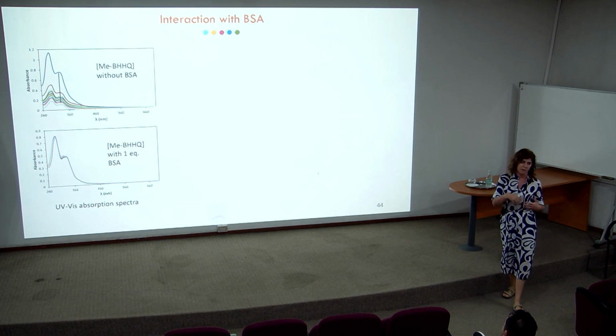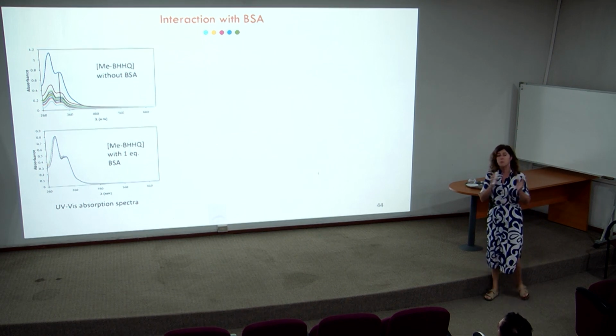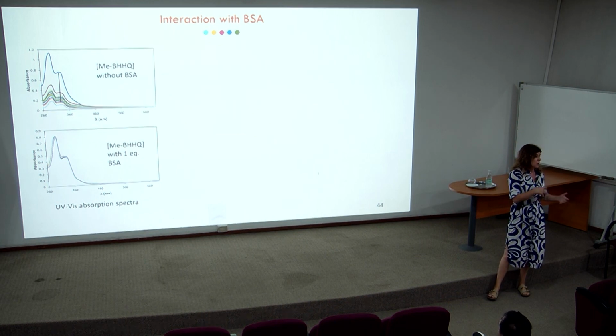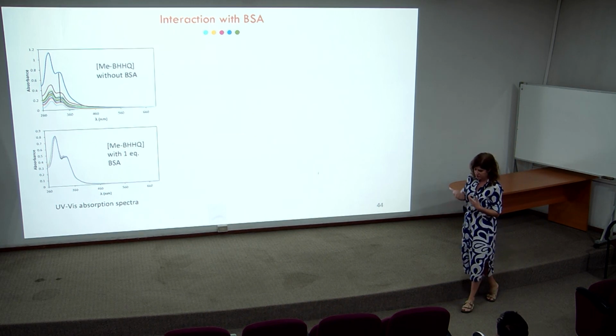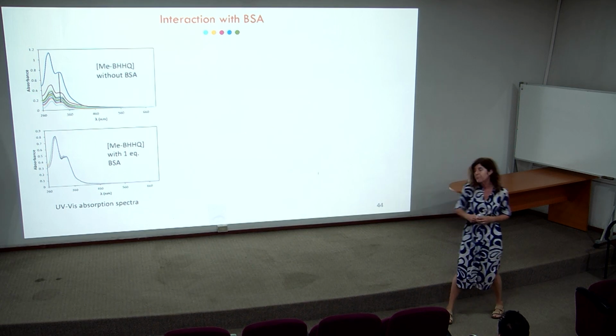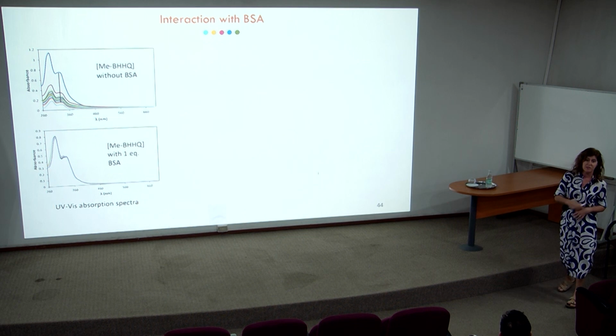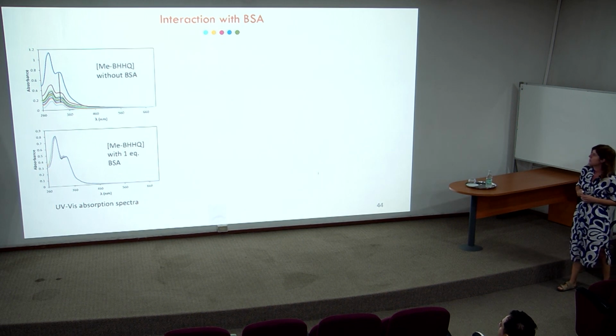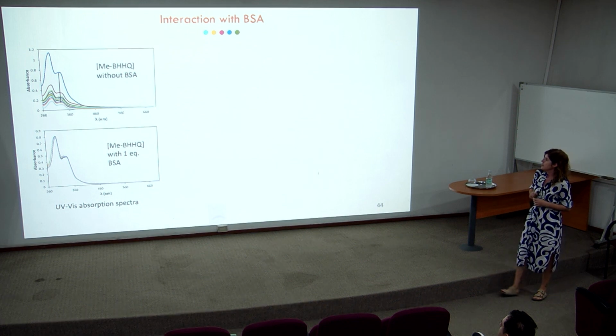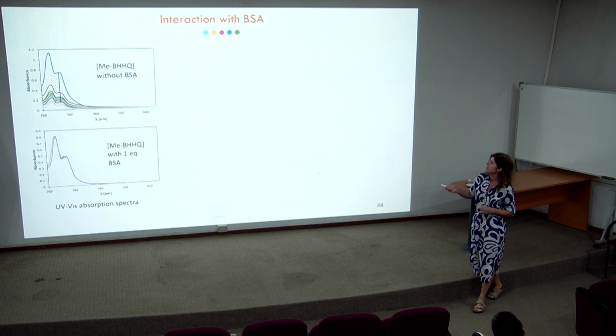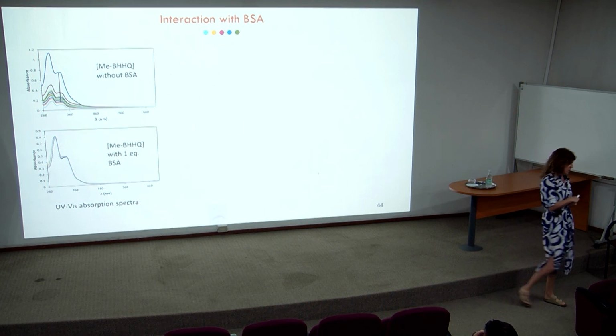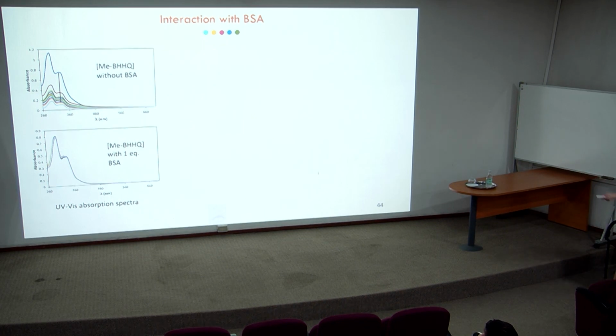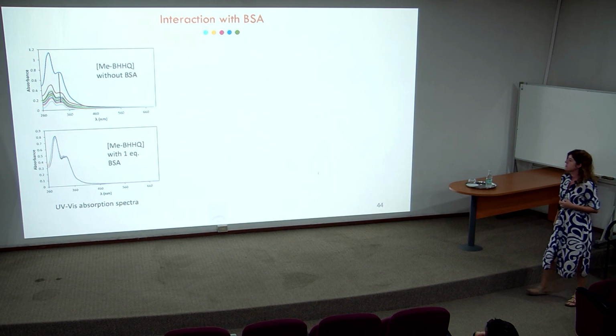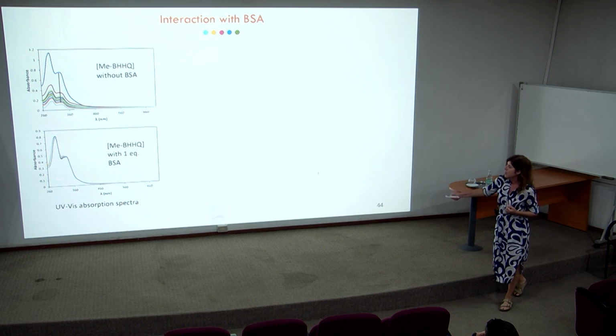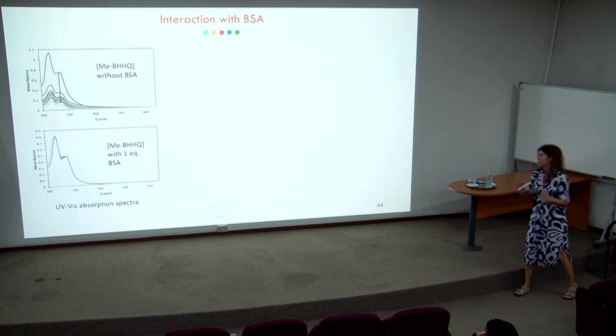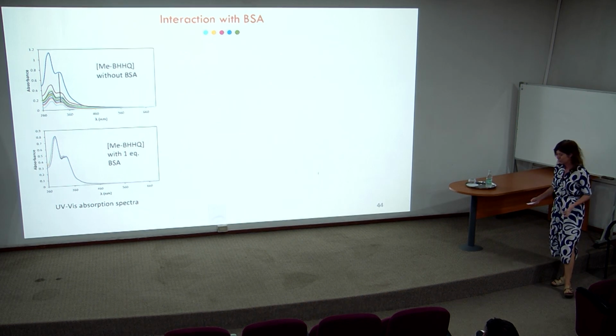We always evaluate the interaction with BSA. Bovine serum albumin can be considered a model also for the human serum albumin, which is the most abundant protein in blood serum, and it is a transporter of many drugs. So we always evaluate the interaction with bovine serum albumin, and we can see that in the absence of BSA, there is precipitation of the complexes, the vanadium complexes, but in the presence of one equivalent of bovine serum albumin, we can see that the spectra are more or less the same. So the compound is kept in solution.